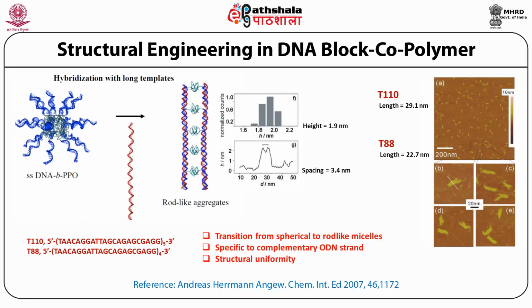If you look at the AFM, you can see the length of that particular rod like micelle is something like 29 nanometer, but in the case of T88, the length of the rod like micelle is less. And look at this height image: the height is something like 1.9 nanometer, and you can also look at the spacing between two parallel strands, which you can figure out. The spacing between two parallel strands is 3.4 nanometer.